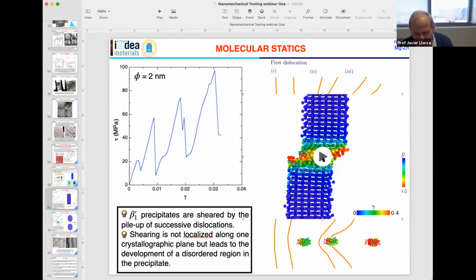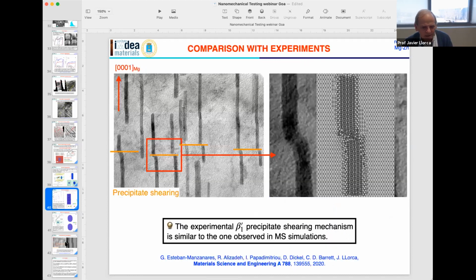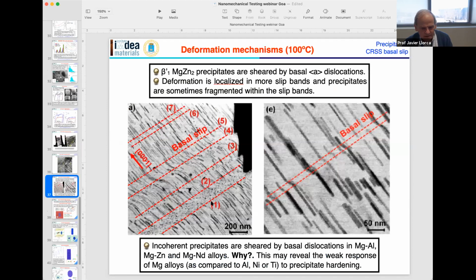It's not that they cut them. You can see, if you go to this TEM image here, this is high temperature, but this is the same. You can see in this region here, the precipitates have almost disappeared. So the stresses were so high that they have been, or here you can see the precipitate has been kinked. So this is not crystallographic slip within the precipitate. This is just pure stresses, brute force, so to speak.